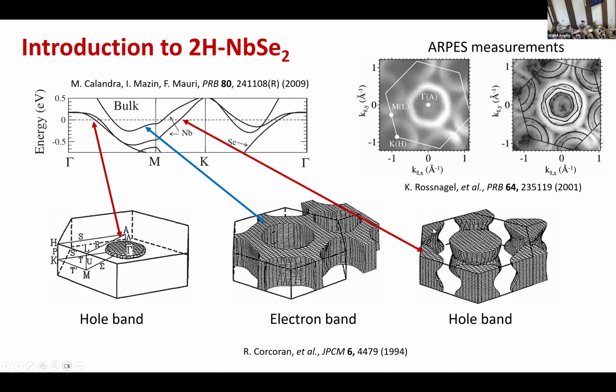So this is essentially for the bulk niobium diselenide. Here, I think it depends on the calculation. Some calculations show there is a kind of band crossing, but not in all the calculations. So essentially, I think for experimentalists, we just think this system has several hole bands and several electron bands. This is, I think, sufficient. And also around the K point, which we will mostly focus on, the hole band is the most important band.